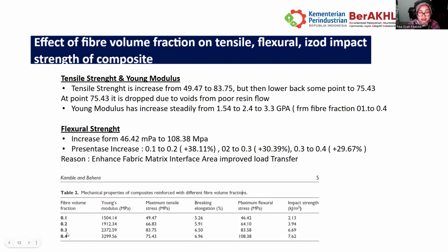And then at the fiber volume fraction 0.3, the maximum tensile stress is 83.75. Now for the fiber volume fraction 0.4, the maximum tensile strength is 75.43. So there is a gap here, a lower point, from 0.1 up to 0.4. The team mentioned that the Young's modulus steadily increases from 1.54 to 2.4 to 3.3 GPa.